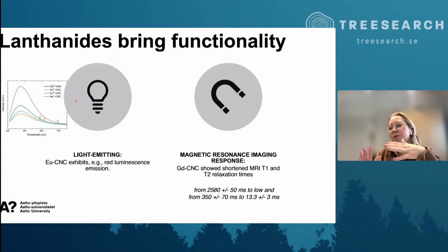The question then, or I think the outstanding question, is the coordination environment. With the gadolinium, we had collaborators who work with magnetic resonance imaging, and we could see that there are very much shortened relaxation times, which implies that they are active substances in an MRI. Whether they could really be used for imaging is of course a matter of a lot of other investigations that have to be done. However, this is a property that we could verify.